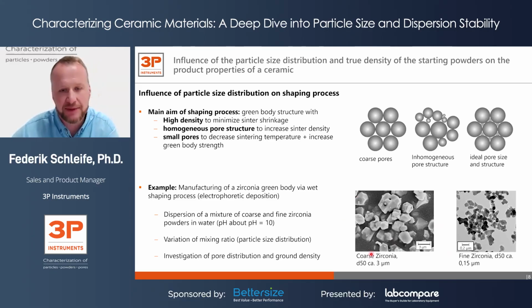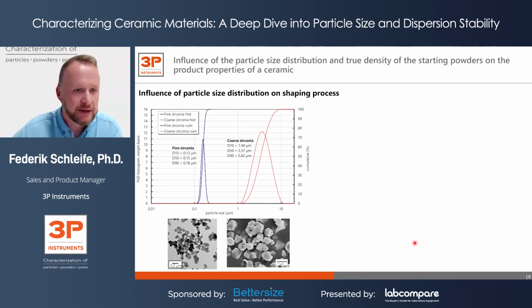So here you see some electron microscopic images of this coarse zirconia with a D50 of around 3 micrometer, while the fine zirconia comes approximately with a D50 of 150 nanometers, or 0.15 micrometer. So on this slide, on the left-hand side, you can see the size distributions of the pure coarse zirconia and also the pure fine zirconia next to each other. And again, the microscopic images.